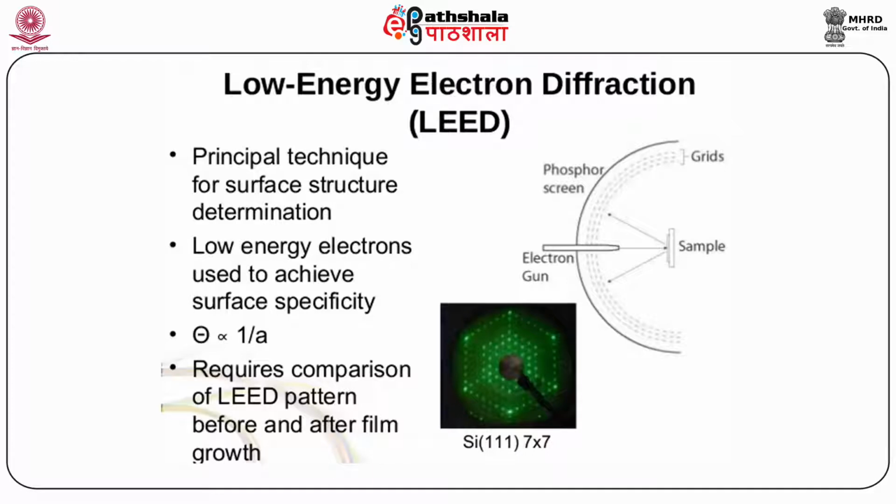With this method, we can determine an exact position of atoms, relaxation, adsorption position, etc. The dynamical approach has a statistical error of 0.02 angstrom in the determination of atom position in the direction perpendicular to the surface.